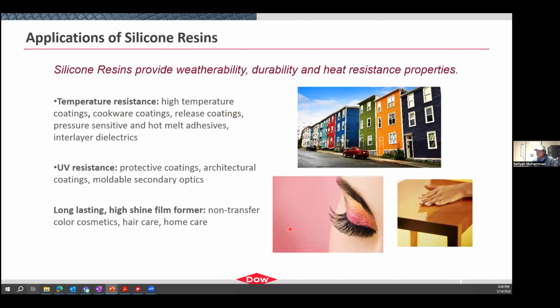So if we think about some of the applications of silicone resins, we often use them when you need to provide durability. So whether that's durability to weather, durability to scratch resistance or heat resistance, right? So some of the areas that we use them in, if you've seen an oven or you've seen a grill, you notice that it has a coating on it or like a paint. Silicone resins are the base of those materials because they are able to withstand the high temperatures that it is exposed to. So we often coat cookware with silicone resin-based coatings. We also have spaces like adhesives, so pressure-sensitive adhesives, and hot melt adhesives for thinking about building applications.